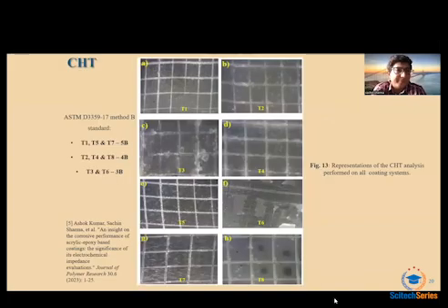So then the final test was done, which was the crosshatch test according to the ASTM D3359-17 method B standard. A tape test was also conducted to measure the surface adhesion of the coatings to the metal substrate. And we could see that T1, T5, and T7, which were A, E, and G, exhibited 5B ratings, which means there was zero detachment of flakes, which indicated that the coatings were intact.